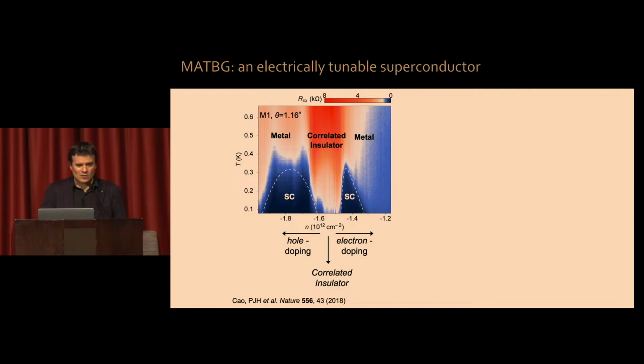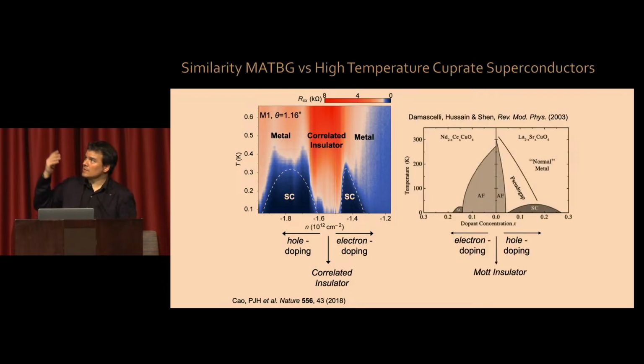So it is also very special because this superconductivity is electrically tunable. Superconductors usually are not electrically tunable, but here I can tune it. Do I want a superconductor or not? Depending on this voltage knob, how many electrons I put in it, it happens next to this insulating behavior. And the entire physics community knows that that behavior is very reminiscent of the behavior of high-temperature cuprate superconductors, where the superconducting behavior happens next to a correlated insulator behavior, okay?